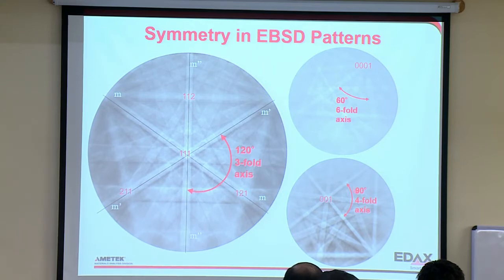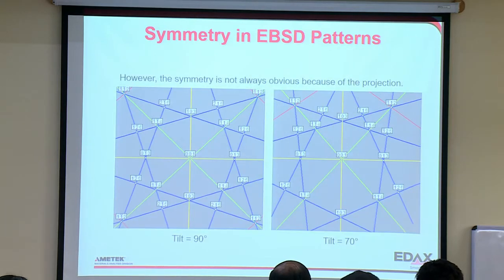Here's an 001, which is a fourfold axis, and you can see that there. You have those 90 degrees apart, and these two 90 degrees apart. And this is an 0001 axis, so I have a 60 degree rotation. So you can see this in the patterns, but because of the 70 degree tilt and where the camera is located, it's not always obvious, and you kind of have to let the computer do this for you.